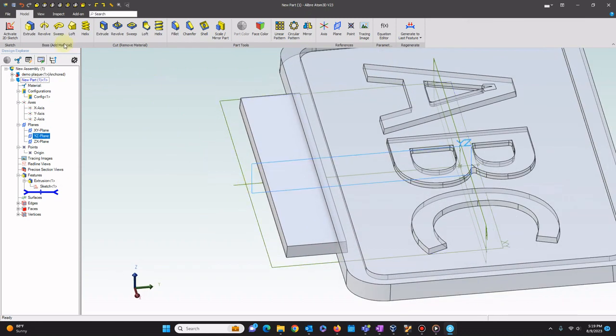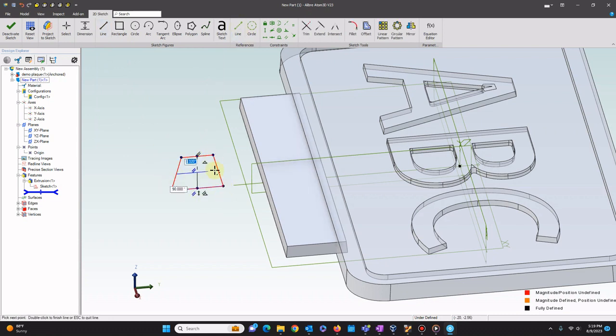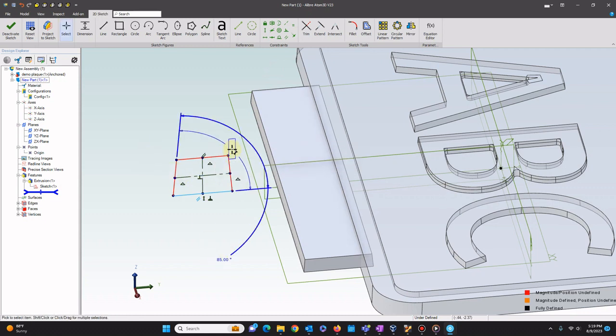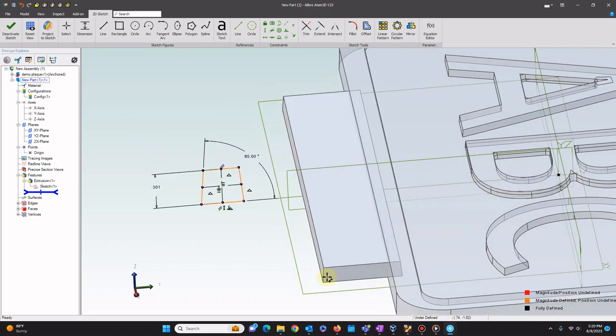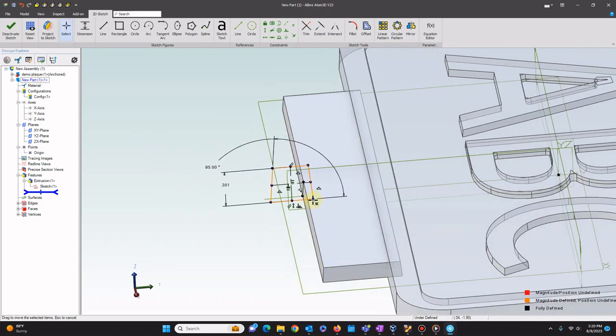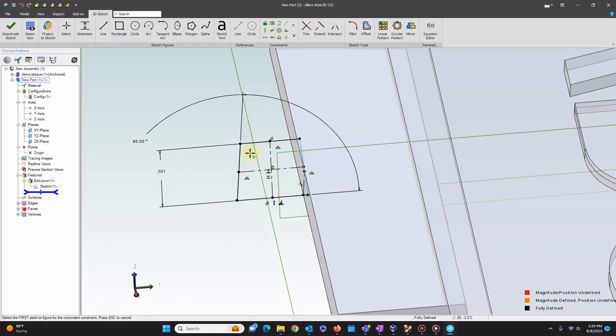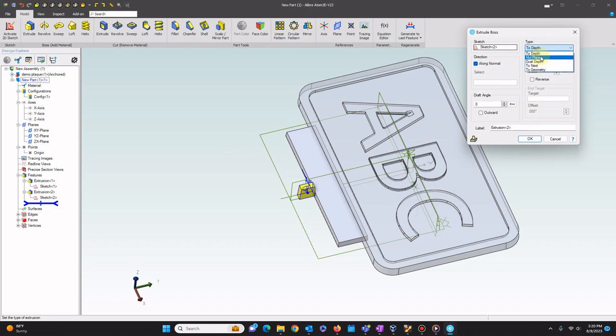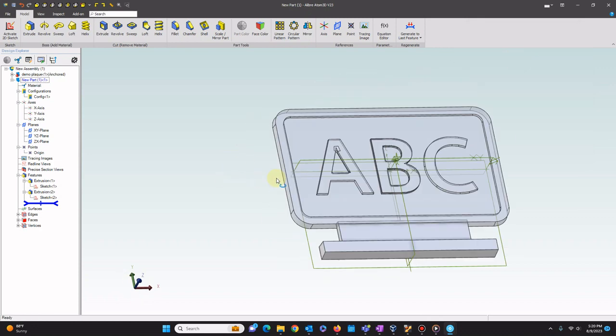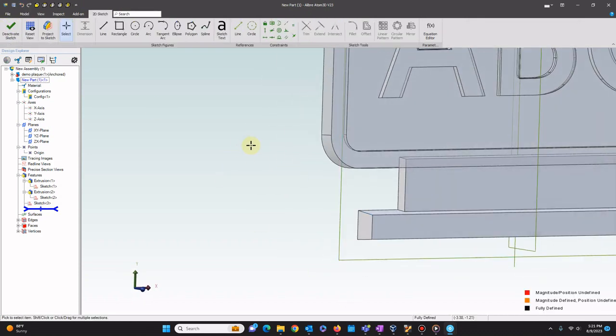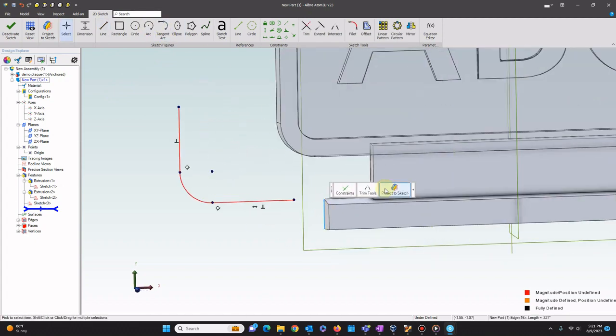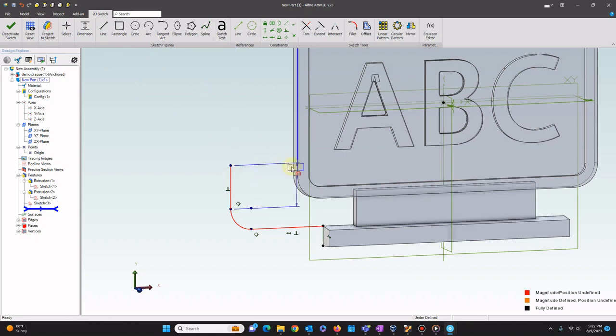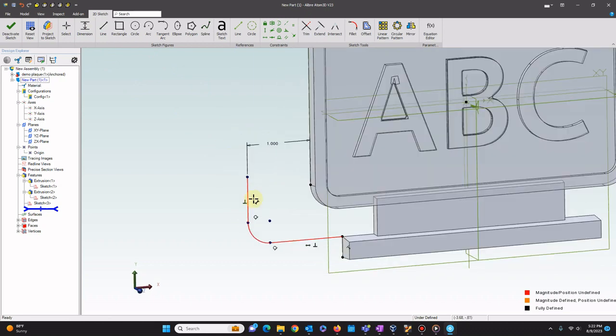Once this is done, we can start the runner by extruding the cross section with dimensions defined in the spreadsheet. A trapezoid with equal height and center width gives us the correct area and allows us to add draft. Finally, we extrude the runner cross section in both directions just beyond the gate. Now we can define a transition from the runner to the sprue by sweeping the runner cross section. Being able to easily put a radius here is one of the advantages of a vertical mold.